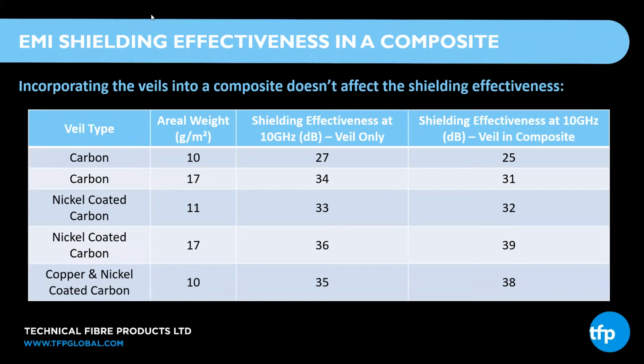So you can see by increasing areal weight, we get an increase in shielding effectiveness, going from 10 to 17, 11 to 17. You can see moving down the series from carbon, nickel-coated carbon to copper and nickel-coated carbon, we see an increase in shielding effectiveness.